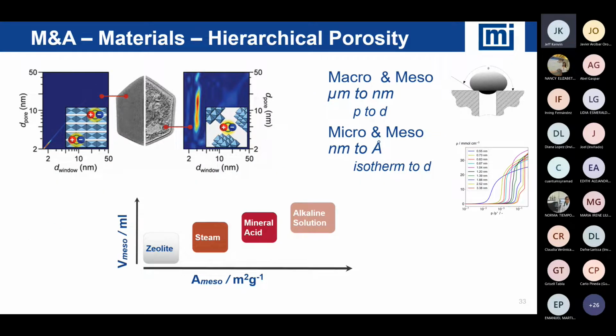Okay, one area that remains great potential for everyone for modifying materials is if you start with a microporous material, can we introduce porosity, and specifically meso and macro porosity, to improve the transport properties of the material? While microporous materials are wonderful for size selectivity, catalysis, separations, where they suffer is rate. Because those pores are so small, when it comes to the practical application, they are rate limited.